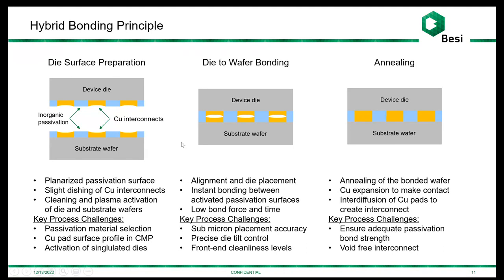So there's three basic process modules that are required in order to achieve a hybrid bond. The first is the surface preparation. In this phase, we prepare the bonding surfaces on both sides, the device die as well as the substrate wafer, by planarizing. So we need a very perfectly flat passivation structure because these are not compliant materials. They're very hard and non-compliant.